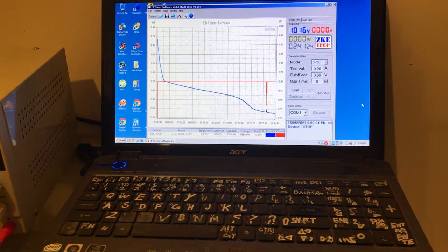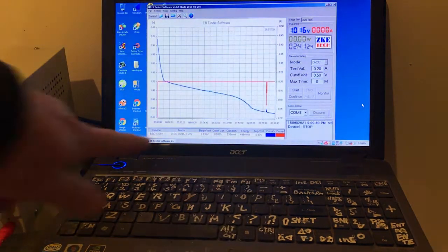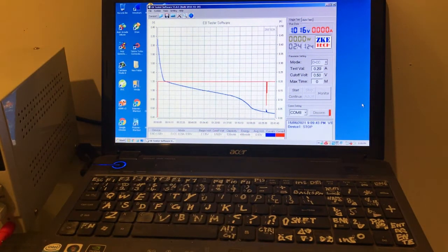Okay, the results from a 7.5 hour charge for a 200 milliamp load: 538 milliamp hours, 499 milliwatt hours. So the 7.5 hour charge sort of did a better job than yesterday's run. So it's still up near the 500 milliamp hours, which is good. It ran for 2 hours and 41 minutes this time. Yesterday's was 2 hours and 23 on a 6.5 hour charge, so an hour extra charge made the difference.